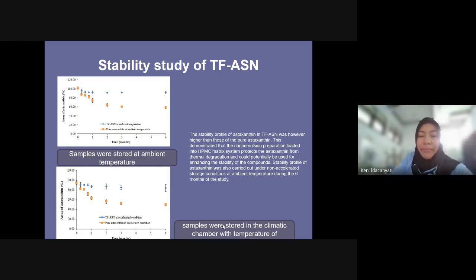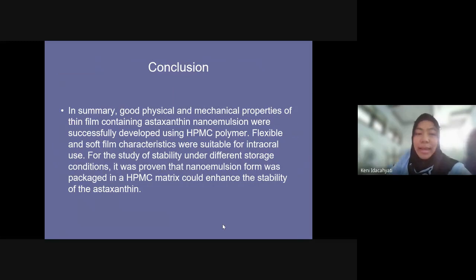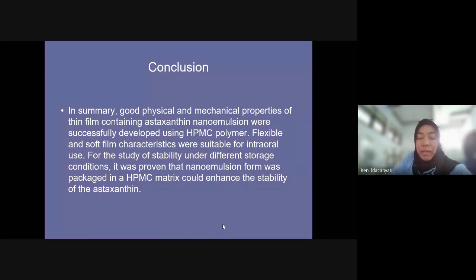the study. The conclusion, in summary, good physical and mechanical properties of thin film containing astaxanthin nanoemulsion were successfully developed using HPMC polymer. Flexible and soft film characteristics were suitable for intraoral use. For the study of stability under different storage conditions, it was proven that nanoemulsion loaded in the HPMC matrix could enhance the stability of the astaxanthin.